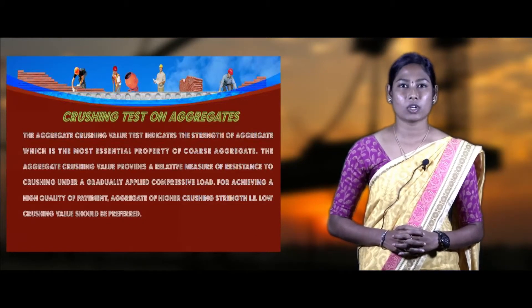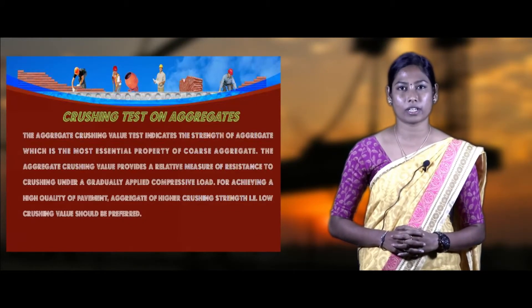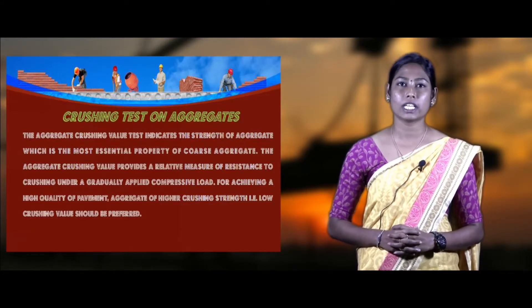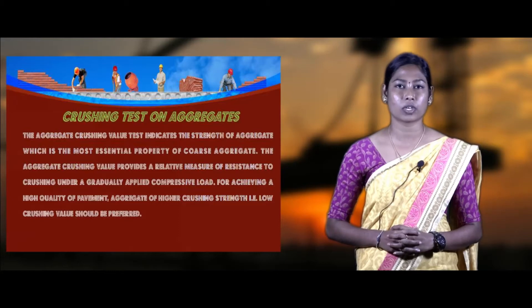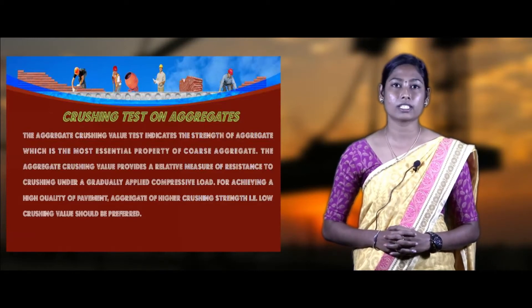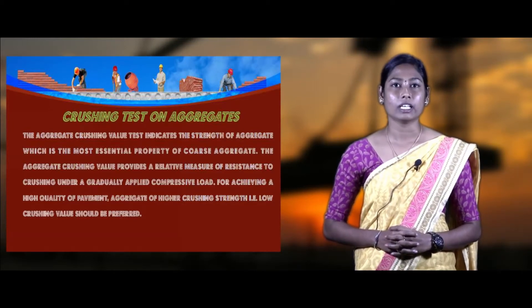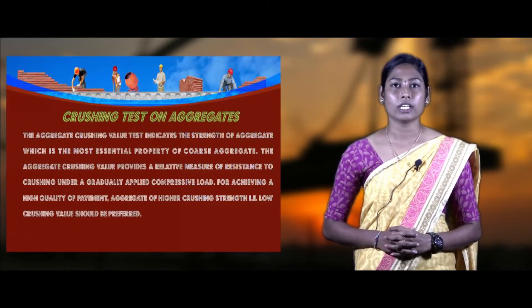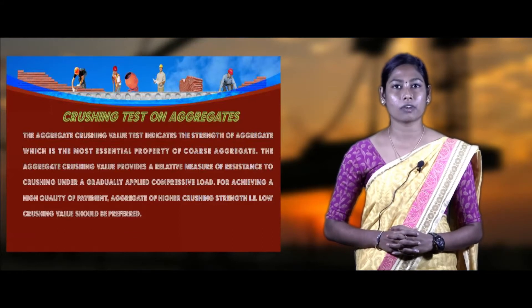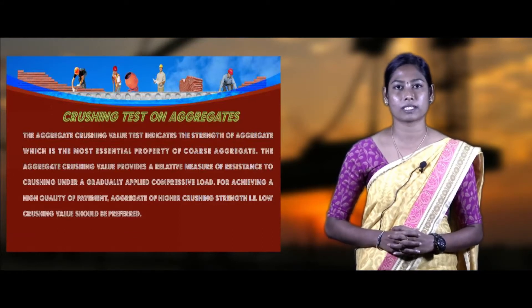The crushing strength of aggregates shows the strength of aggregates, which is the most important property of aggregate. It provides the relative measure of resistance to crushing under compressive loads. For achieving high quality roads and pavements, aggregates of higher strength should be preferred — that is, a low crushing value. Low crushing value means higher strength. It indicates lower crushed fractions under applied loads, giving longer service life and more economical performance.